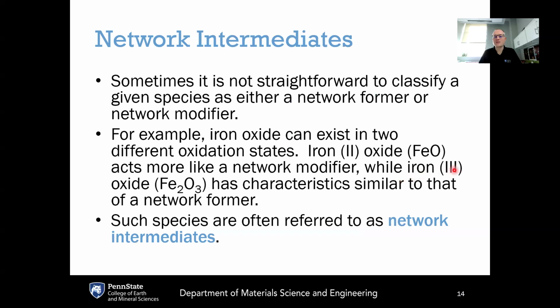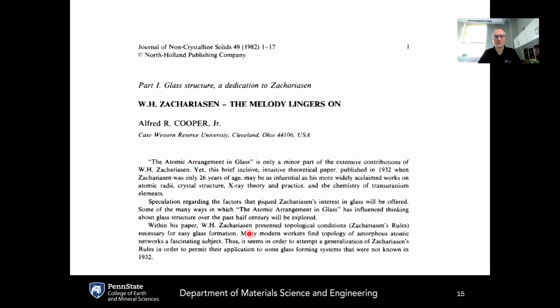However, iron can also have an oxidation state of +3, and iron 3 oxide is Fe2O3, and that behaves more like a network former. So iron can switch between behaving like a network modifier or a network former, depending upon its oxidation state. And therefore, we refer to this as a network intermediate. So we've got network formers that form the backbone of the glass network, network modifiers that modify the connectivity of the network somehow, and then network intermediates, which could play either role in the glass structure. Now, I want to return to Al Cooper's paper here.